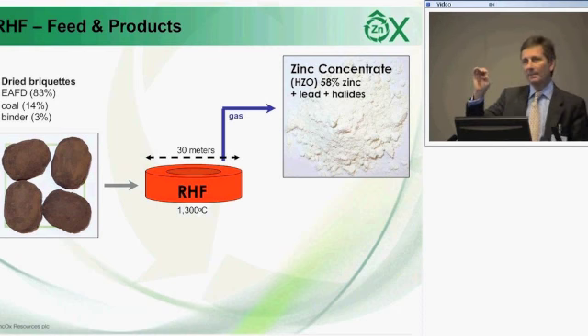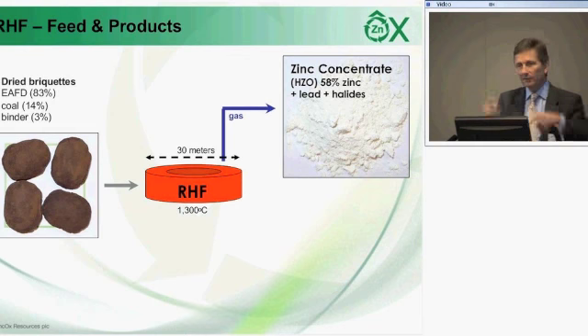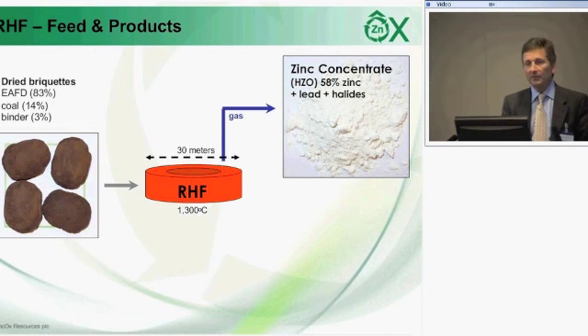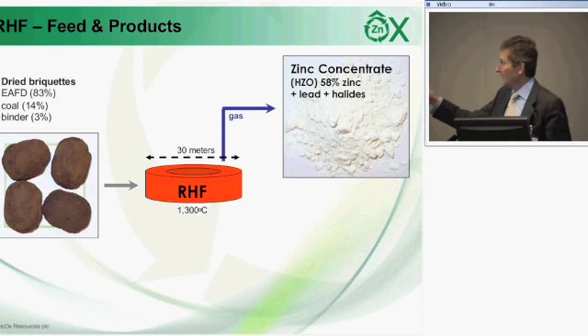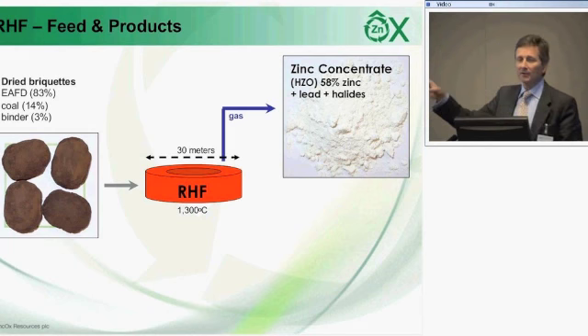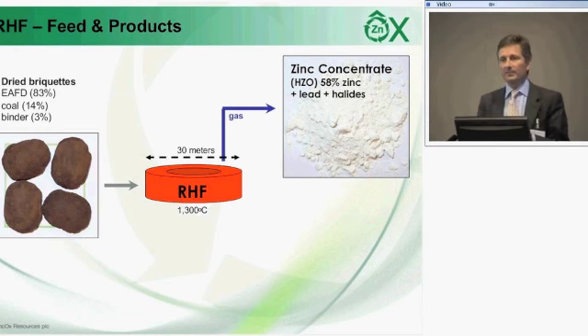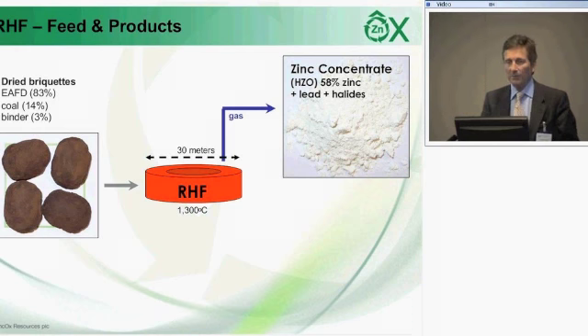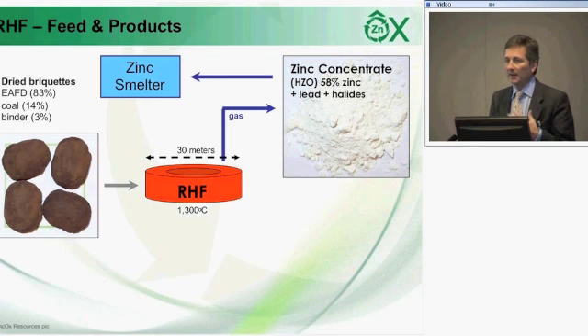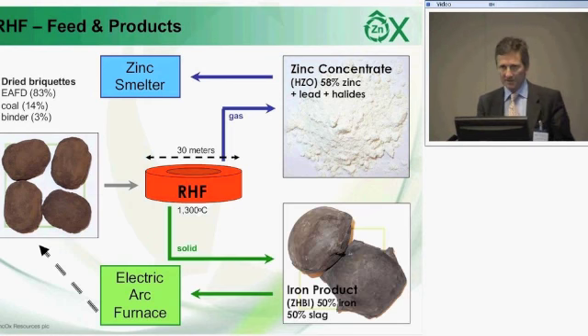It's desiccated, it's lost about 50% of its mass, and you squeeze that through another set of briquetting presses into a larger briquette, which we can sell back to the steel mills that gave us the dust in the first place. So because we've metallized the iron, and that's about 50% iron, of which 85% is metallic iron, it's a simple remelting operation to recover the iron. And the lovely thing about the process, of course, is, as you've probably gathered, there is no waste. So when we go to see environmental agencies about permitting, when we tell them what we're doing, they get pretty supportive and excited.